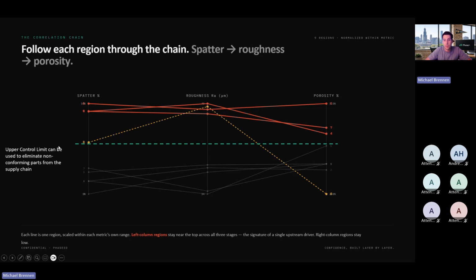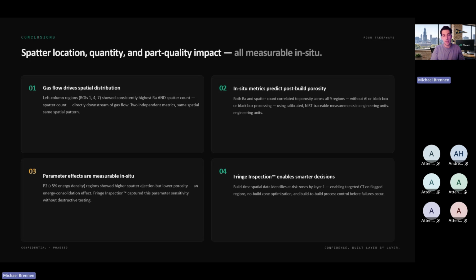And you can see how you would begin to be able to set upper control limits in your process to say, parts 3, 5, and 8 and 4 were all good, whereas our parts 1, 7, and 4 were off nominal, out of our process control window. So this is a very basic experiment of one build, but it already begins to demonstrate how some of our customers are using the technology to set upper and lower control limits in their manufacturing process. We can begin to correlate in-situ metrics with ex-situ metrics. This is what we get asked every day.